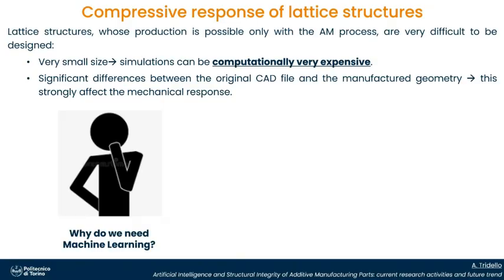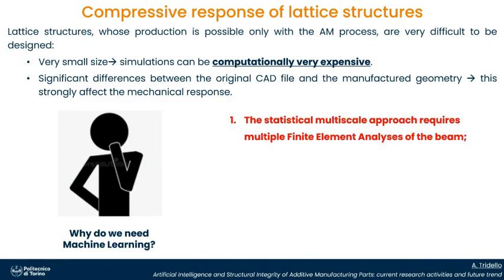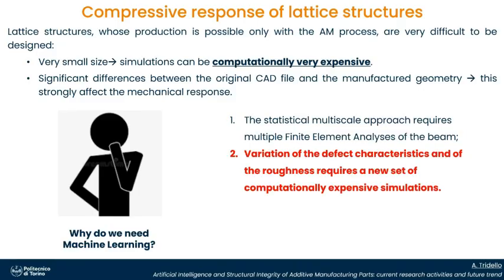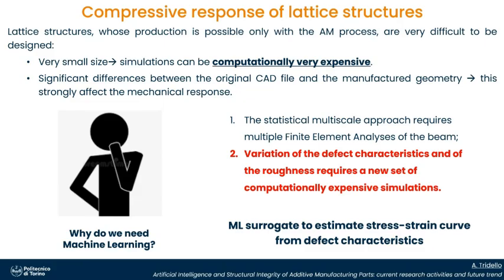But why do we need machine learning? This activity seems to be completed, okay? The statistical multi-scale approach requires multiple finite element analyses of the beam, and the variation of the defect characteristics and of the roughness requires a new set of computationally expensive simulations. Machine learning can be used as a surrogate model to estimate the stress-strain curves from defect characteristics.